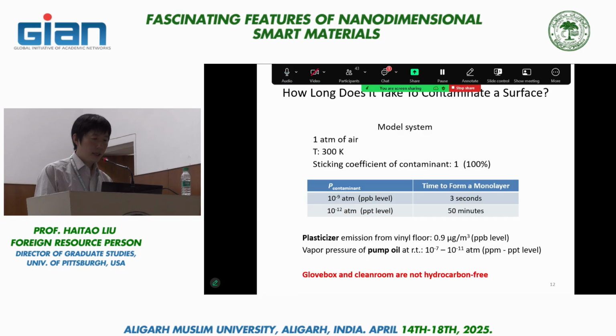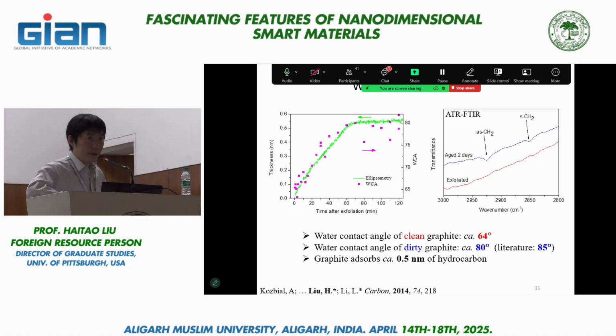And here you see these dotted data points, and those are measured on the exfoliated graphite. You see within about an hour, 60 minutes, we recover the literature contact angle data around 80 degrees. On this same sample, we can also do additional characterization, because this is a reflective surface. We can use another technique called ellipsometry, which is a common technique used to measure thin film thickness on reflective substrates. It gives the average thickness of the thin film, so it doesn't tell you the fine structure. But regardless, it shows roughly linear growth of the thickness and plateaus around 0.5 nanometer after an hour. And you see the two data measurements highly correlate with each other, suggesting that the change of wettability is a direct result of the growth of whatever material on the graphite surface.